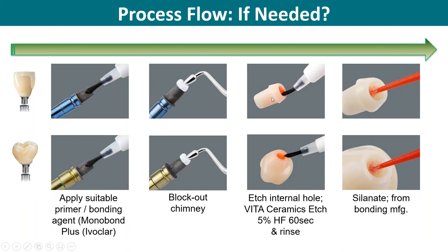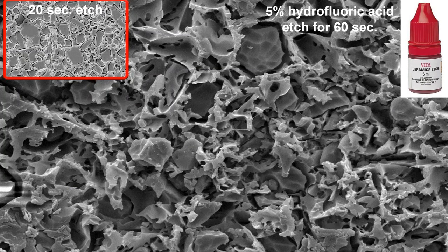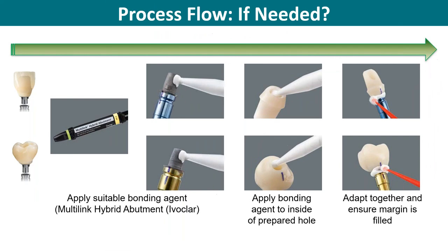But the abutment, whether it's an abutment for a cement retained or a screw retained crown, we have to etch the enamic or any other material you're going to use. It's always etched, it's rinsed out, and then you use a silane. Once you're past that step, you want to make sure that you don't over etch your material. Using a material called ceramic etch, it's only 5%. A lot of offices are going to use 7, 8, 9%. And if you do, which is fine, then you just need to make sure that you only reduce that etching time to about 20 seconds. Because you don't want to over etch it, because your etch pattern, the surface that's left, you don't want it to crumble and fall off with the crown. So etch it properly. It's very important to etch properly the right amount of time.